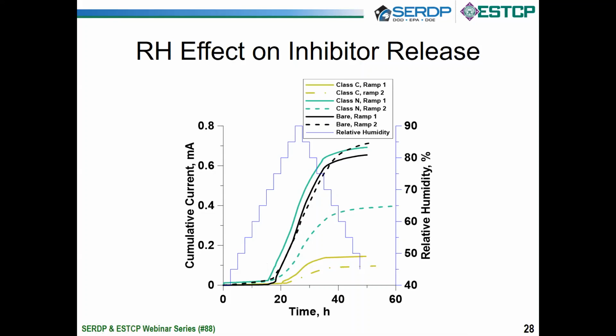The point I want to make, though, is that we added up the current for each cycle individually, okay? So this is not cycle 1, and then I add cycle 2 on it. This is just the current in each cycle. So the first thing I want to point out to you is the solid black curve. This is a coupon with no coating system on it. And you can see that that current increases as we go up and down. And as you're going up in the high humidities, you can see this cumulative corrosion current increasing. And then as we dry off, it stops.